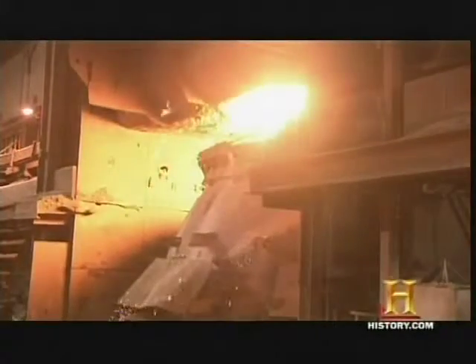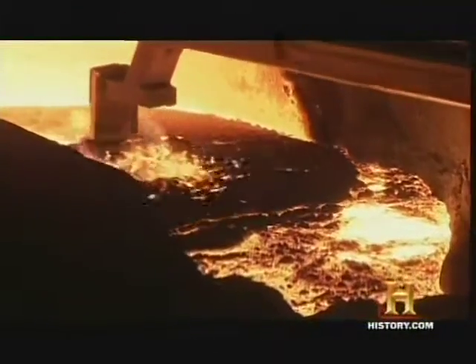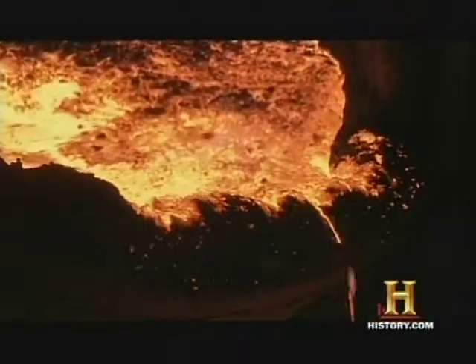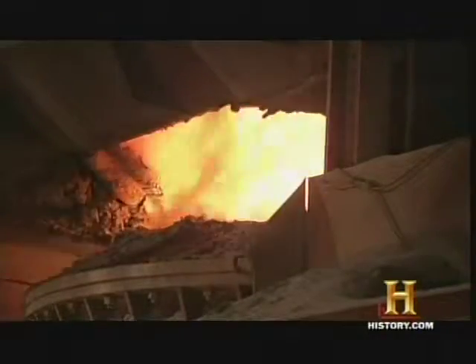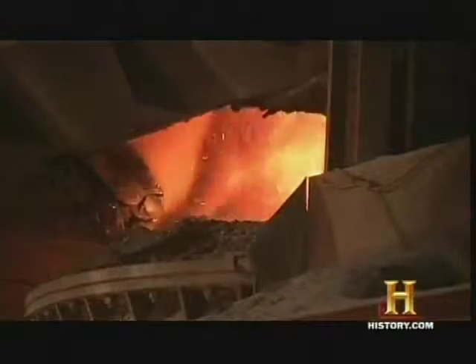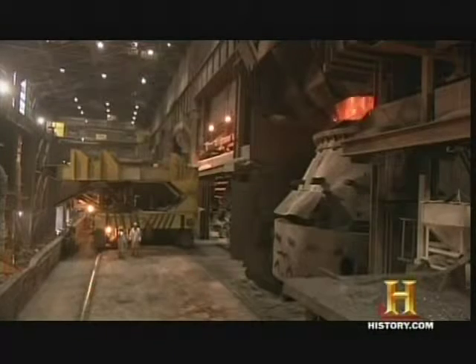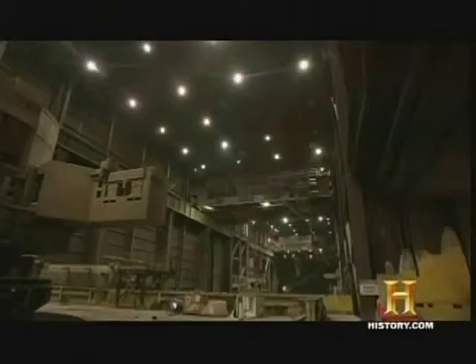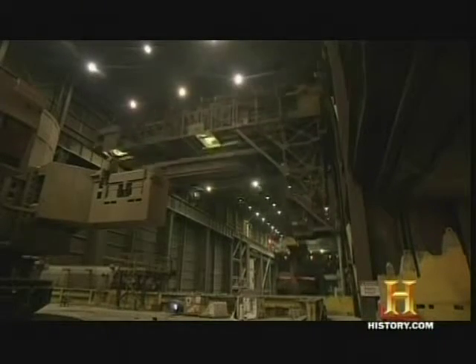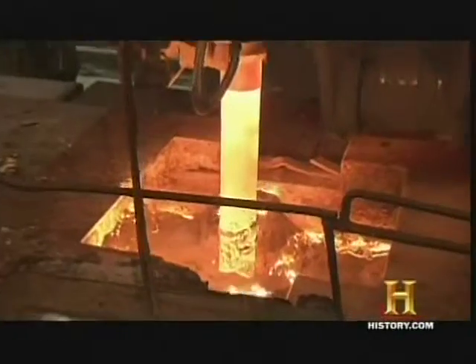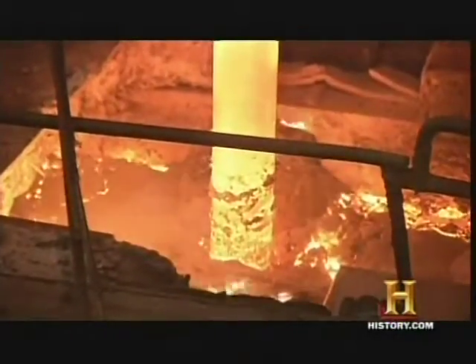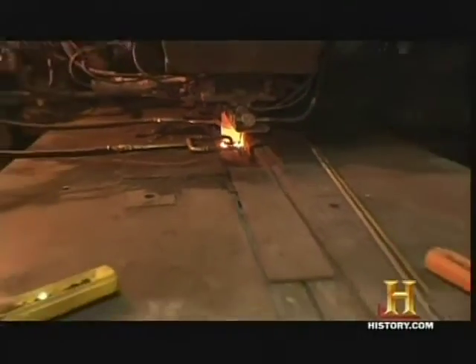In addition, the steel shop lines the bricks with a layer of a steel-making byproduct called slag. This includes impurities such as carbon, silicon, and various oxides. About 30 years ago, the furnaces lasted about 700 heats, 700 cycles between rebricking. Now we're able to make between 20 and 40,000 heats on a furnace lining by just using the waste material to coat the brick. After the oxygen furnace, the slightly cooler steel will be further refined and transported in other brick-lined vessels before being allowed to solidify in a casting mold.